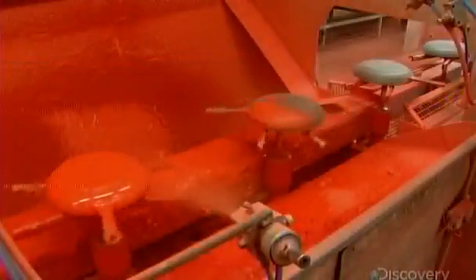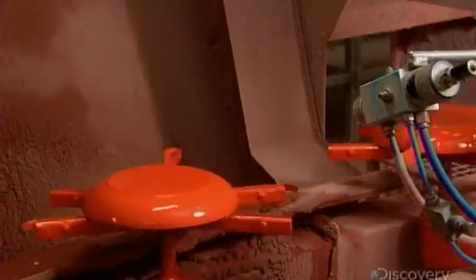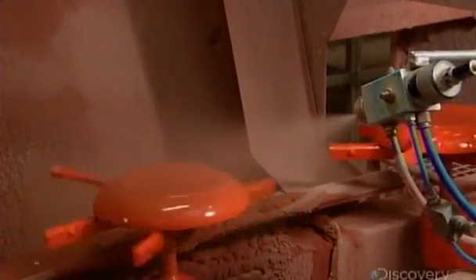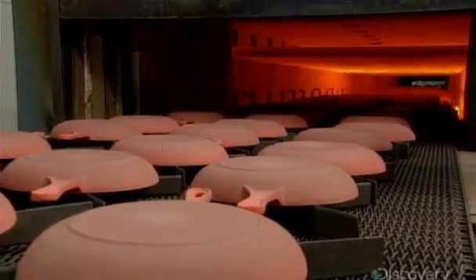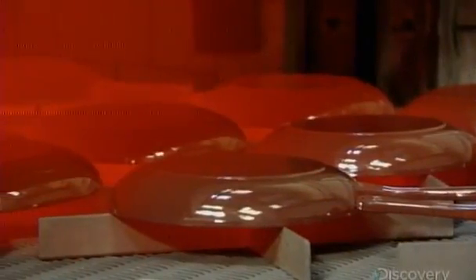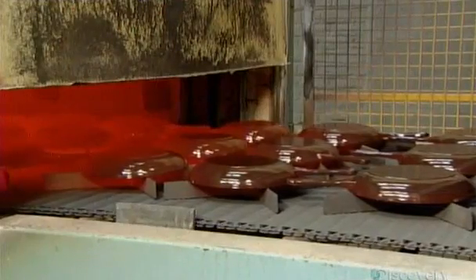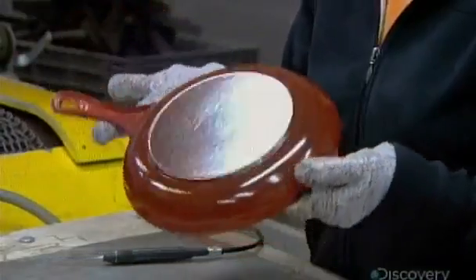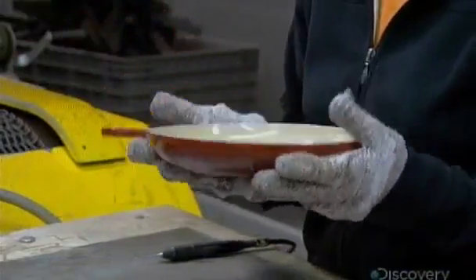The iron recipe contains a high level of the mineral silicate, which helps the enamel adhere well. Once again, the cookware goes through the dryer, then into the oven at 850 degrees Celsius for about 45 minutes to vitrify the enamel. Once the cookware cools, it undergoes a final visual inspection, the last of 30 quality control checks throughout the production process.